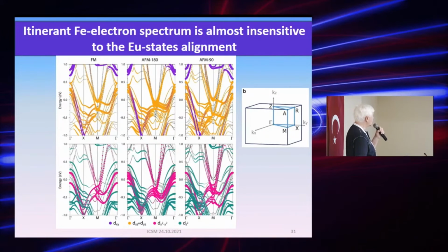Now the calculations can be done for various types of magnetic ordering. Here 3 examples are given. The first is a fully ferromagnetic type ordering between europium planes, and the second is anti-ferromagnetic, pi angle. The third is pi over 2 type, where the magnetic moments rotate to a perpendicular direction from plane to plane.